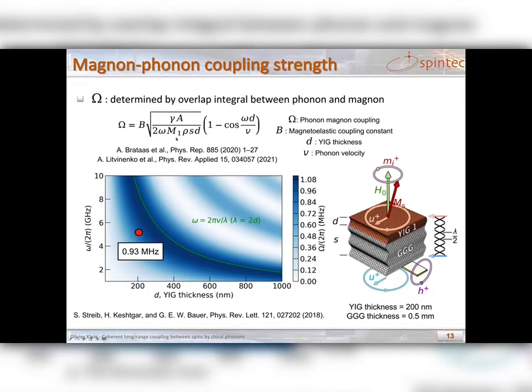It is given by this overlap integral between the phonon and magnon wave functions, and it is calculated to be like this. Here the cosine term is quite important. When it is -1, omega becomes maximum, while when it is 1, omega is 0. So here is a plot showing omega as a function of YIG thickness and frequency. And the green line is the case where the cosine is -1 and the overlap integral is maximum. What it corresponds to is when half of the acoustic wavelength is the same as the YIG thickness, as shown, for example, in this illustration. So the overlap integral between the Kittel mode and acoustic mode is maximized in this case.